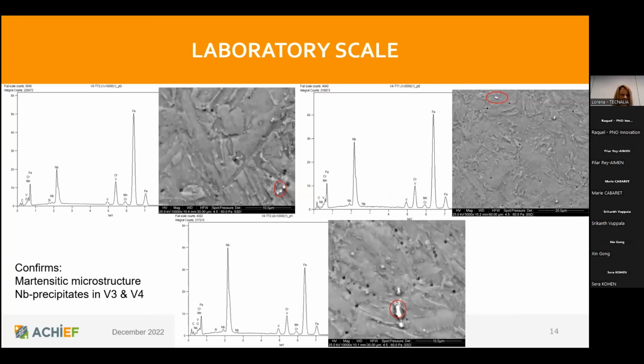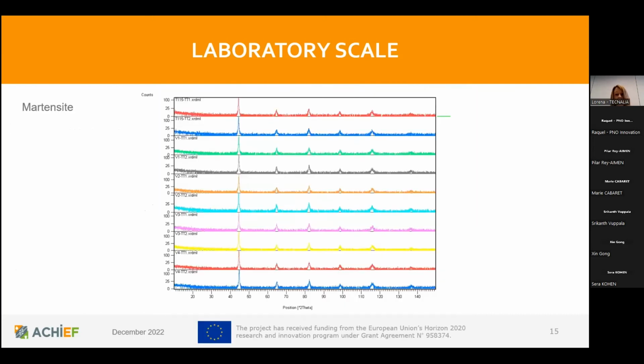The scanning electron microscopy study confirms the predominance of a martensitic microstructure in all cases, with niobium precipitates in those steel grades with niobium in their composition. The X-ray diffraction analysis shows a similar pattern for all the cases with the predominance of a martensitic microstructure in all the steel samples.